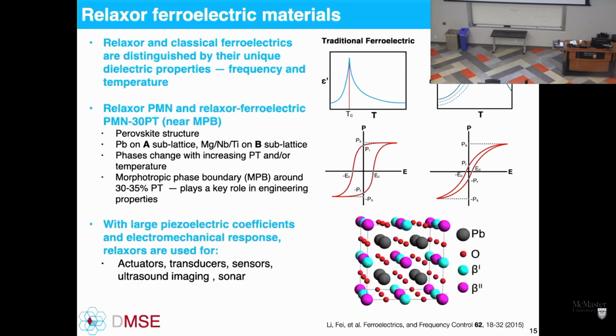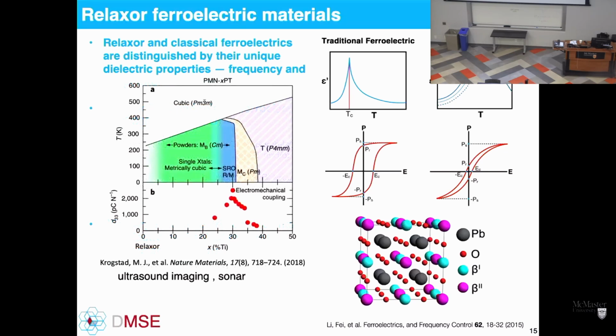Now, in certain cases, particularly in pure PMN, this structure can order locally, where you have one sublattice of B' here that is niobium or magnesium rich, and B'' is niobium rich, and it's not really fully ordered anywhere in the material, but you get this doubling of the unit cell as a consequence. And as a function of temperature and titanium content, you can change the properties of the material remarkably, where you get a dramatically enhanced electromechanical coupling at around 30% titanium or PT content in the material. You have a range of phases present from a rhombohedral to monoclinic to tetragonal on the higher PT content side.